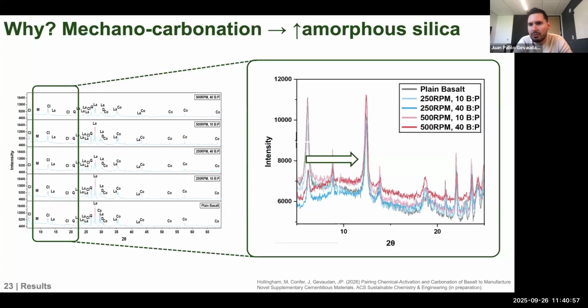And what we can see again for the higher ball to powder ratio of 40, which is that darker blue and darker red that you're seeing here, is a slight shift towards higher 2 theta values, which could signify that there are some shifts in the amorphous content of our basalt here. Now, this is still under development, and we have some other FTIR data campaigns going on right now to really verify that and look at that amorphous content.